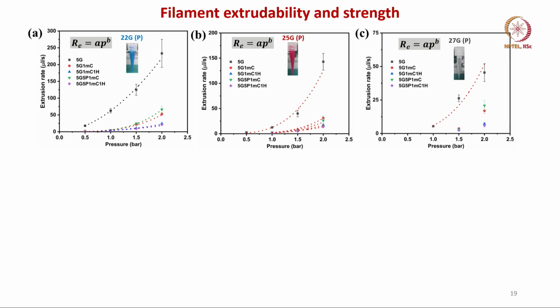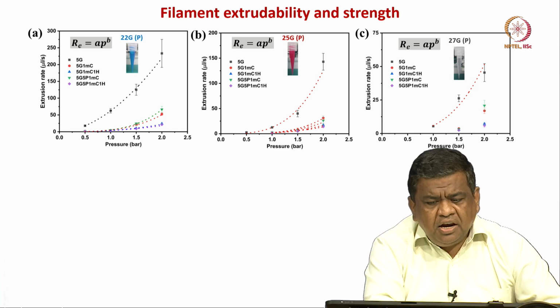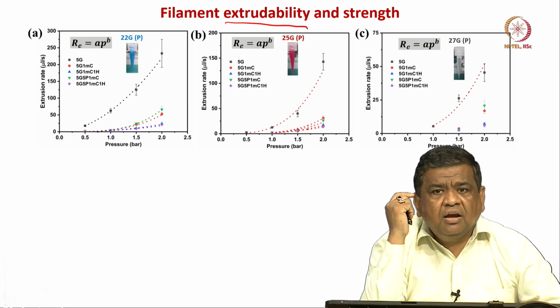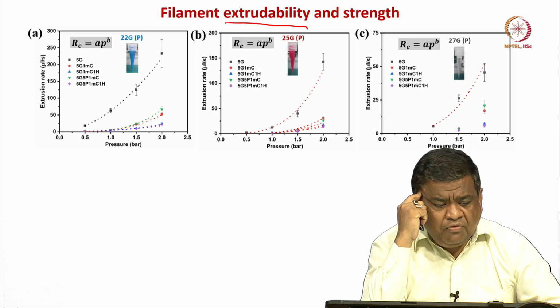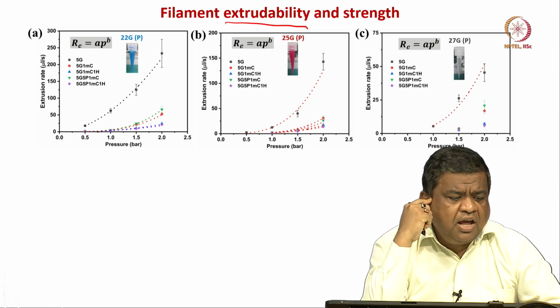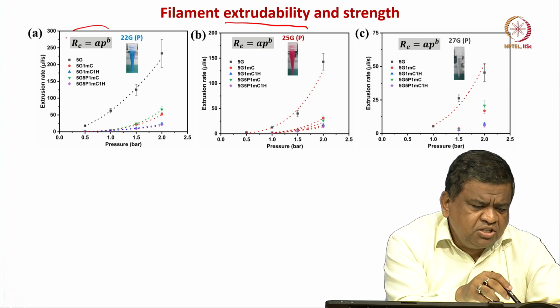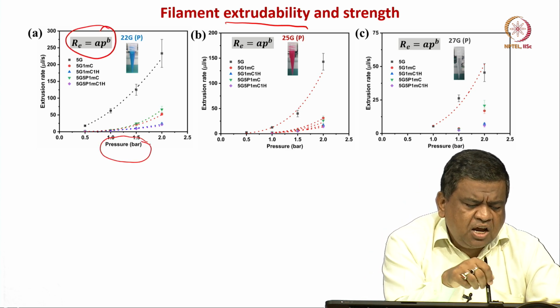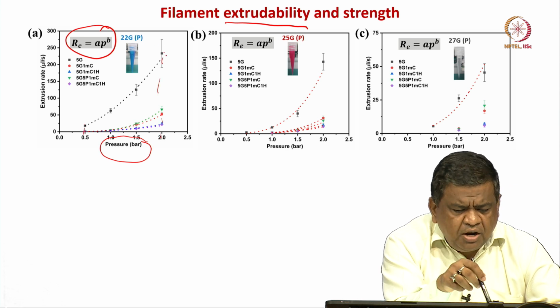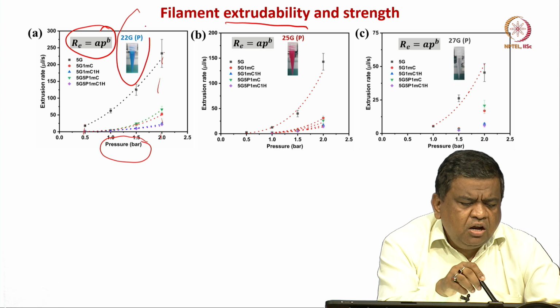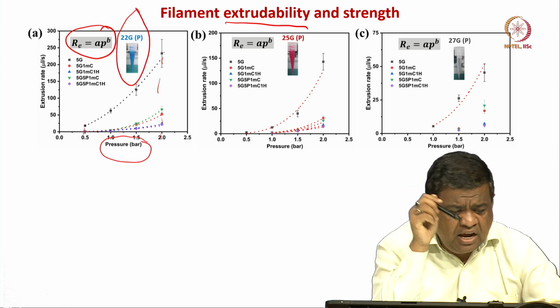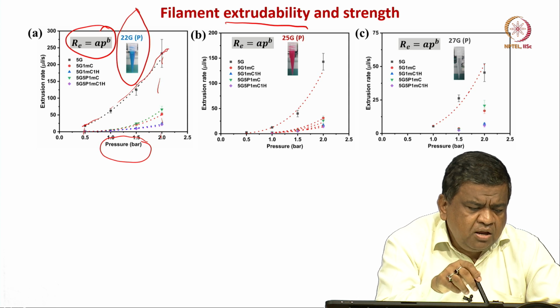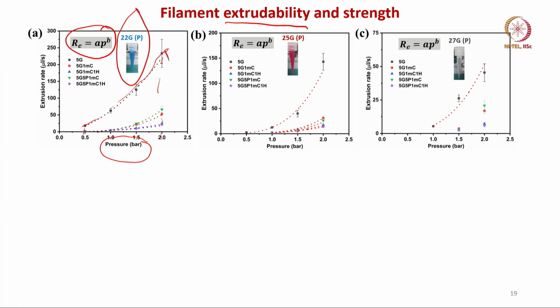Now, when I taught you about the process science of 3D extrusion printing, I mentioned very clearly that filament extrudability is one of the main things, and also filament strength. So, filament extrudability and filament strength were carefully analyzed, and extrusion rate was plotted against extrusion pressure up to 2 bar, right. We varied the pressure between 0.5 to 2 bar with a 22 G plastic nozzle, and what you see here is that 5% GelMA has a higher extrusion rate, but this extrusion rate is lowered as you modify the hydrogel composition.